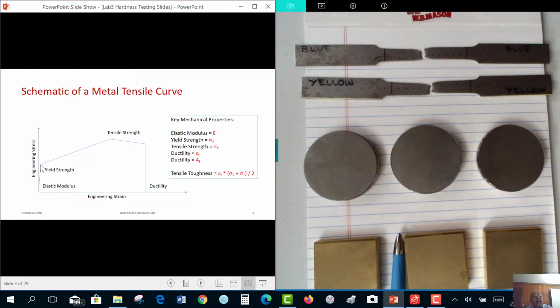And then we saw uniform plastic deformation begin, along with continuing elastic deformation. And it begins at yield strength. This is when dislocations begin to move and multiply, and part of the deformation is irreversible. So this is another material property. And then we reach the maximum stress when non-uniform plastic deformation begins. We still have continuing elastic deformation. And this maximum stress point is called tensile strength of the material. So this is the third important mechanical property.